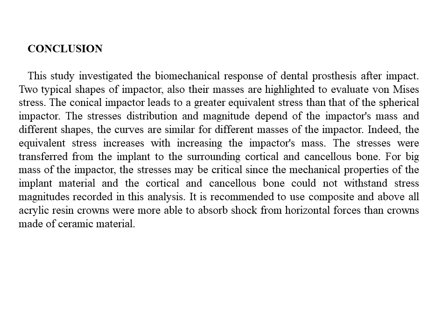It is recommended to use composite and above all acrylic resin crowns, which were more able to absorb shock from horizontal forces than crowns made of ceramic material.